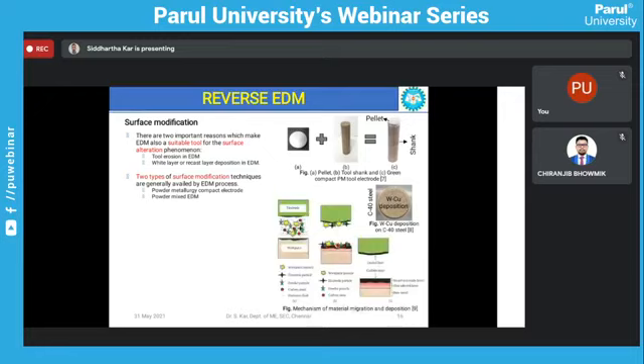If we see the phenomena of surface modification by powder metallurgy or powder mixed EDM, as represented by these several bubbles, there are the workpiece particle, the electrode particle, the powder particle, and the carbon atom. The carbon atoms are basically dissociated from the hydrocarbon oil. Hydrocarbon oil is nothing but the dielectric medium. Hydrocarbon oils such as kerosene and EDM oil are used. So carbon atoms get dissociated from the dielectric fluid after it undergoes ionization, and these carbon atoms are also deposited over the workpiece and tool surfaces.